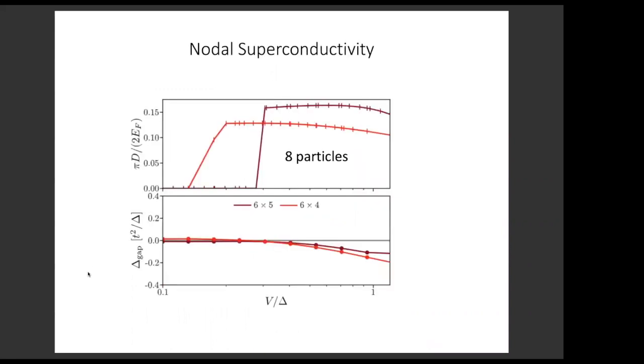Also, as we increase the particle density, we find an interesting case that in the large range of interaction strength, we see that the superconducting stiffness is already present, but the pairing gap is either 0 or very small. So this we interpret as the nodal superconductivity. When you're doping above the Van Hove singularity, the F-wave order parameter has nodes. Next slide.